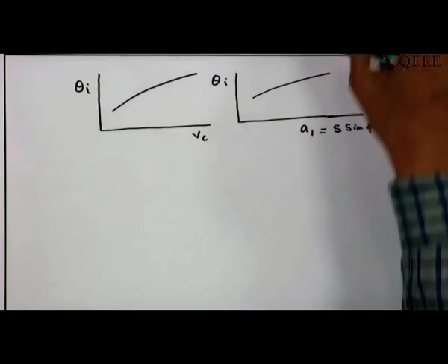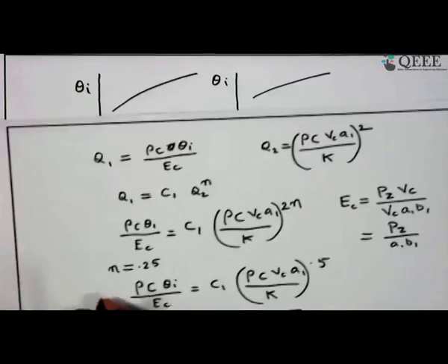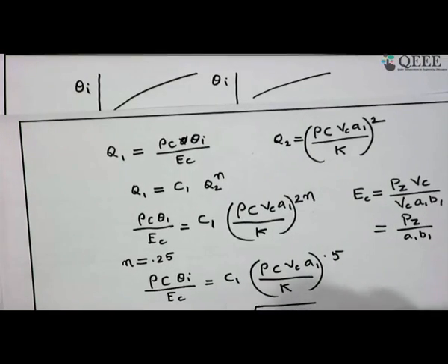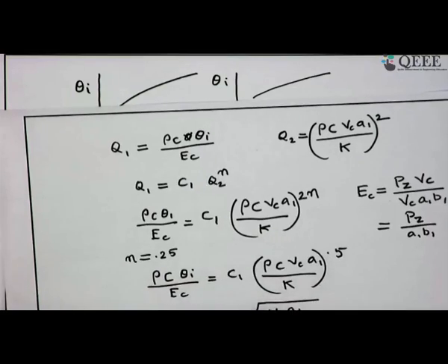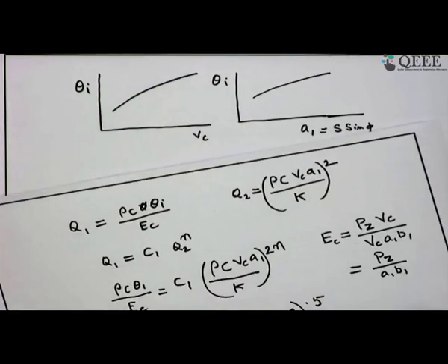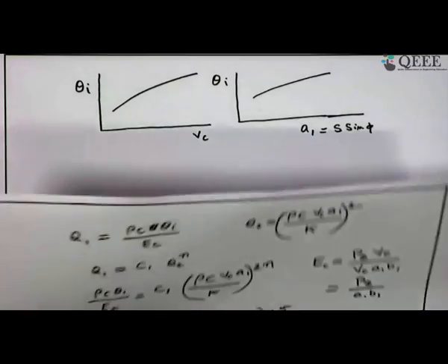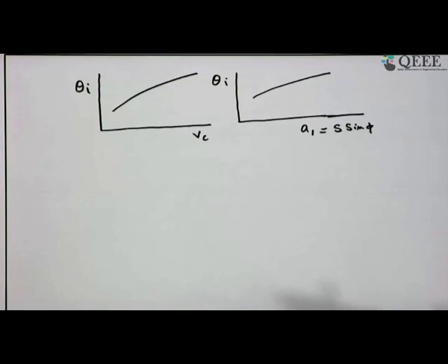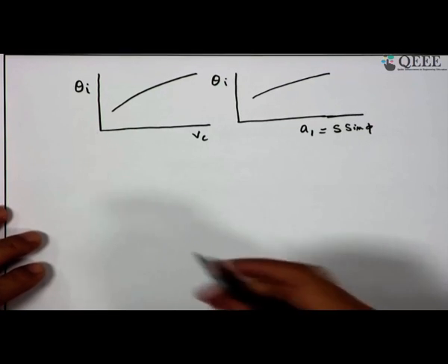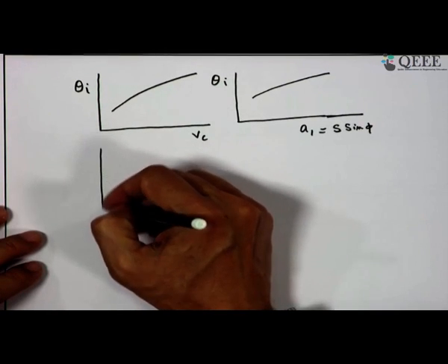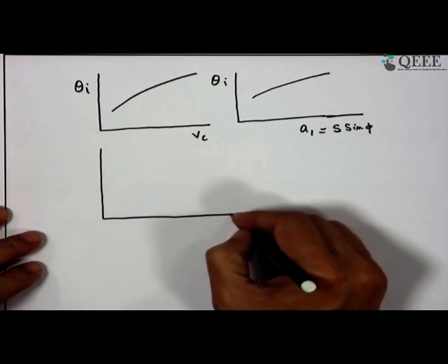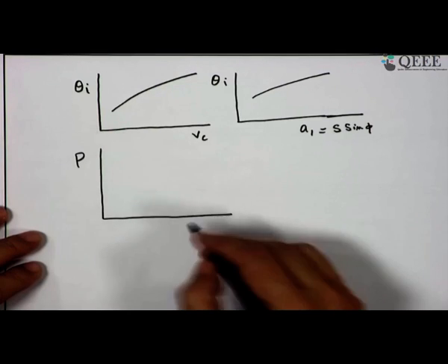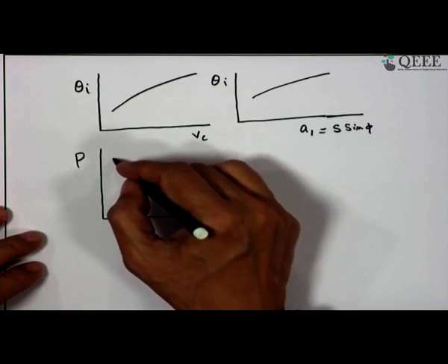Now, this can be supported by this equation where we get an index of 0.5. So this and the experimental results are reasonably matching, and from this we understand the effect of velocity. The effect of velocity is to increase the temperature, but at the same time if I draw the reference of cutting force, then it is simply Pz, and by Vc it is falling in nature.